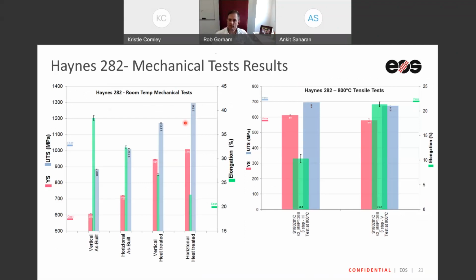So when talking about Haynes 282 in room temperature testing, here's the plot. The pink bar here is for cast. So the pink one is yield, the blue ones are the ultimate, and the green ones are basically your elongation. If I'm talking about casting values, this is the bar for yield strength for casting. And as you can see, we easily beat that. And in terms of UTS, in a heat treated condition, we also beat that. And if you're talking about elongation, that just means that Haynes 282 can meet casting requirements any time of the day.